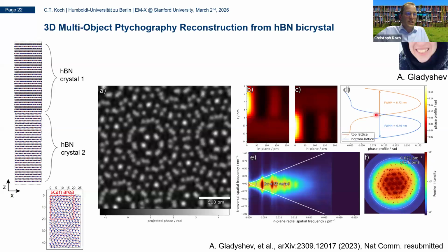And let me show you this also on a different example. So this is now an experimental data set. This is a stack of 2 hBN crystals with a twist between them. This was produced actually by one roughly 9 nanometer hBN crystal, which was folded over so that the folded over part is now twisted with respect to the underlying crystal.